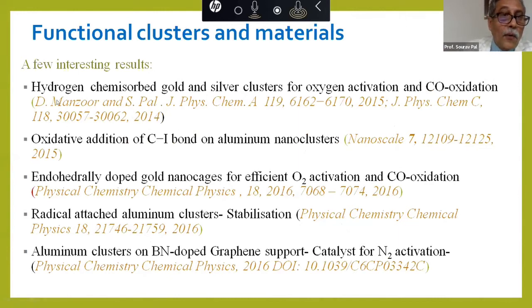So one of the interesting catalysts that we looked at was a small gold and silver cluster with hydrogen atom chemisorbed. Interestingly, these systems are actually being experimentally synthesized today. And we showed that compared to the native gold and silver clusters, if you do a simple hydrogen atom chemisorption, the oxygen activation is very good, and that allows CO oxidation to take place. In fact, CO oxidation has been our hobby problem.